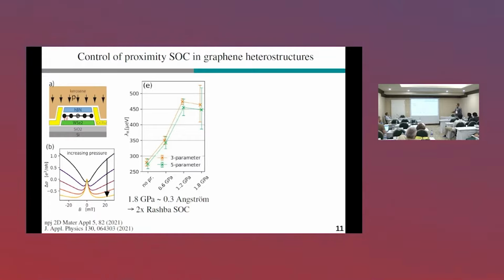If you then do magnetotransport measurements of such a system upon external pressure, you will find a crossover from the weak localization into the weak anti-localization regime. If you then do the fitting of these curves, you will find that the Rashba spin-orbit coupling can be increased roughly by a factor of 2 with an external pressure of about 1.8 gigapascal, which corresponds to a reduction of the interlayer distance by 0.3 angstrom, which is around 10% of the interlayer distance.